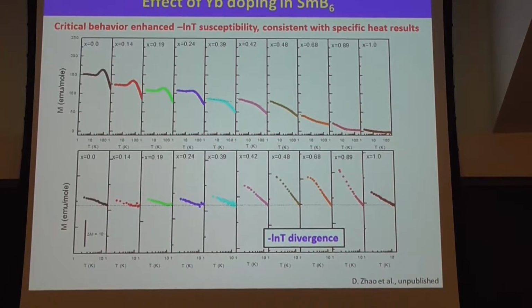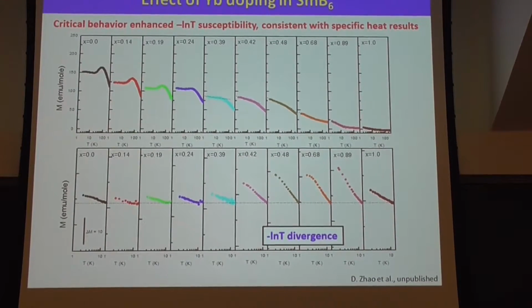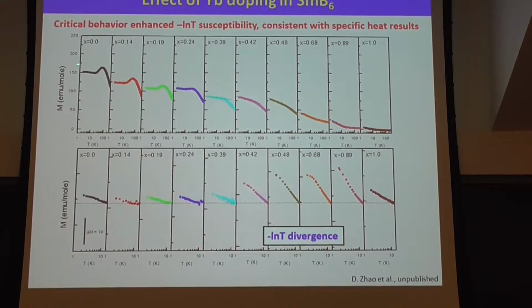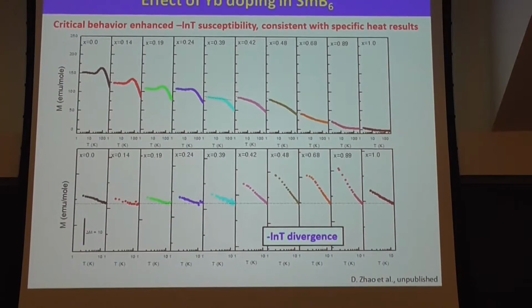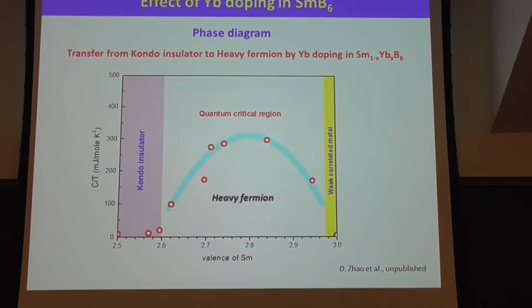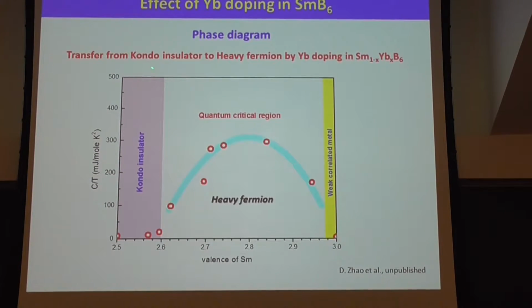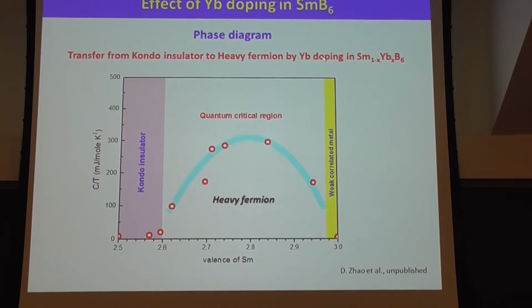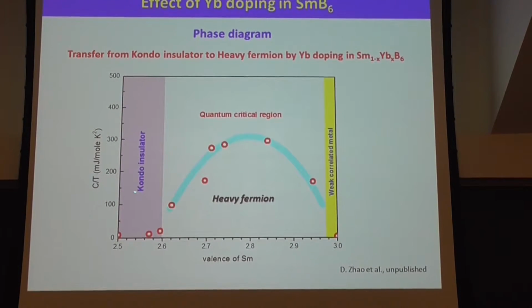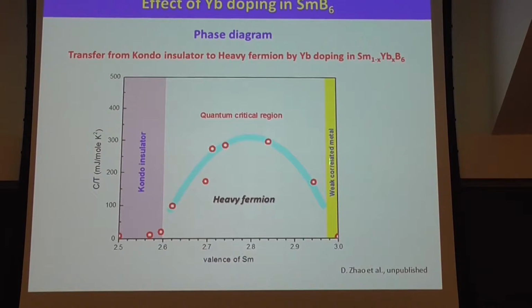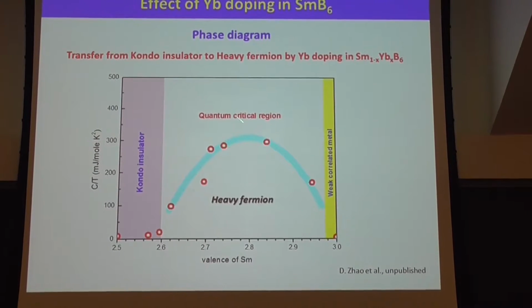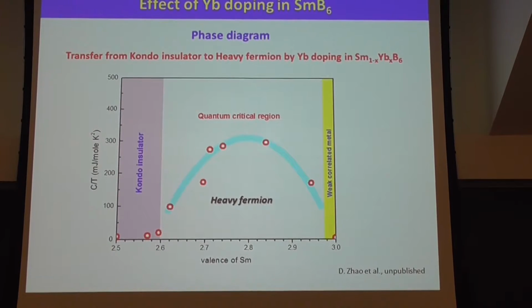All the data show that in Yb-doped SmB6, it goes from the topological insulator to here, where it shows heavy fermion behavior. Then I build the phase diagram here. It transfers from a Kondo insulator to a heavy fermion by Yb doping. In this region the Sm valence is 2.5. This is close to the valence of the Kondo insulator. But between this and the weakly correlated metal, there is a quantum critical region that shows heavy fermion behavior.